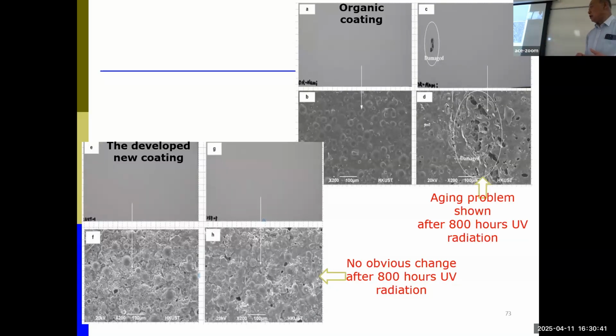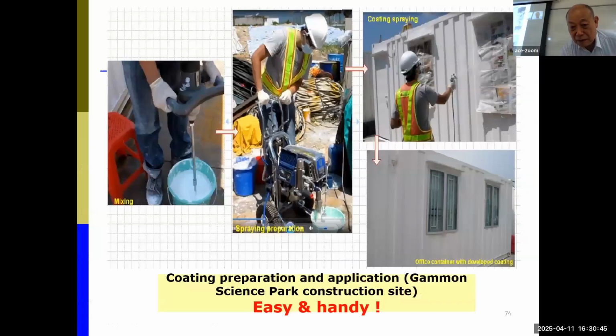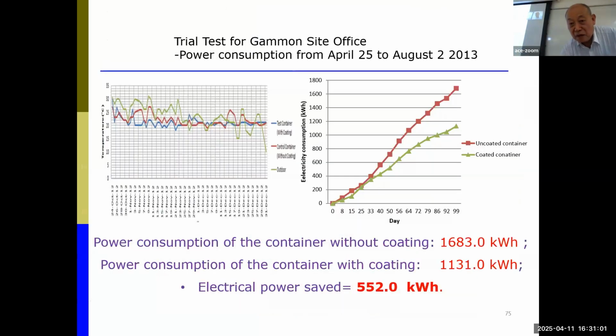But for our material, there's almost no change after. So we did some site tests. In Hong Kong, you mainly see construction sites use containers as offices. So this is on the construction site. We did a measurement. You can see one with our coating, another without.